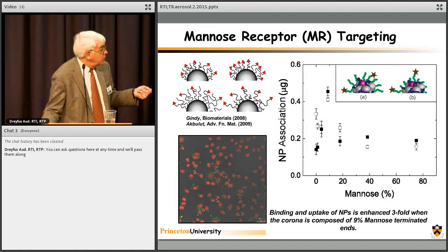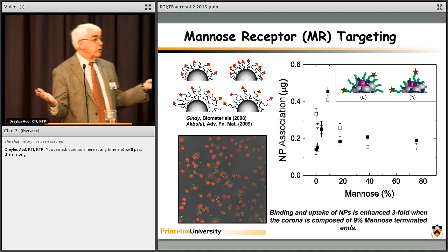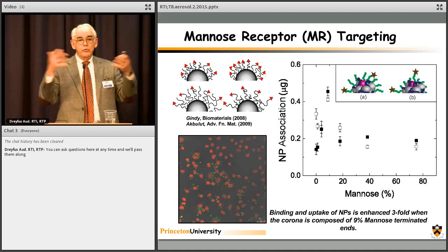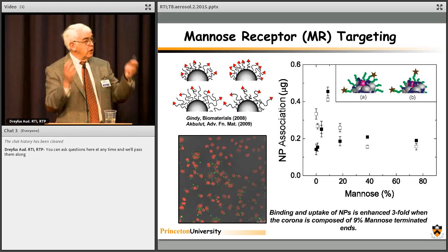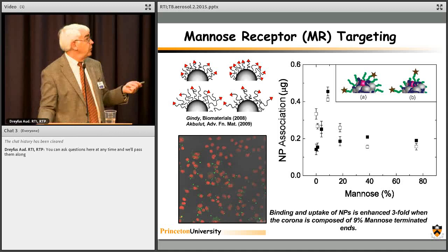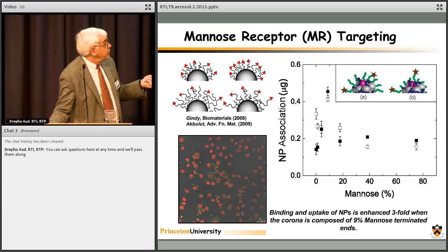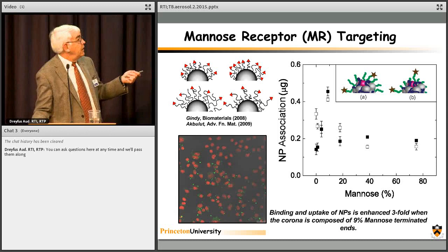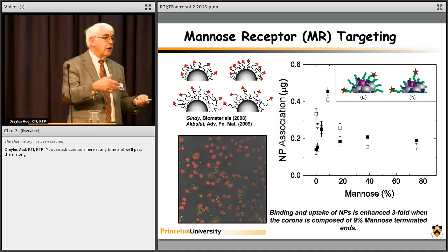So in a morning, we can make this whole spectrum of materials because all we're doing is mixing neutral and mannose PEG, in a way that's difficult for most people who are doing post-conjugation to know what they've done. Putting one mannose chain on a 100 nanometer particle, it's difficult to diagnose what you've really done. So this assembly process is helpful. The black ones are the 5K PEG neutral and the targeting agent on the end of the 5K. We'll just focus on those. So here is without any mannose, and that's basically background. That's just the phagocytosis of the macrophage just sort of gobbling up whatever's in their vicinity.